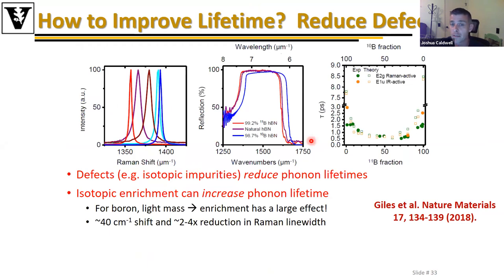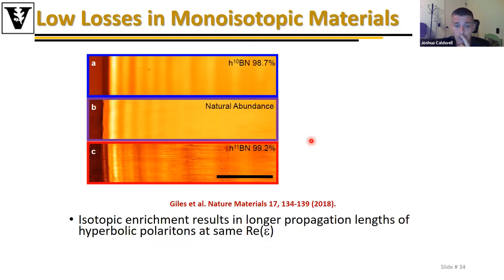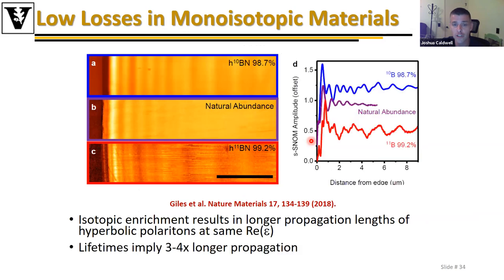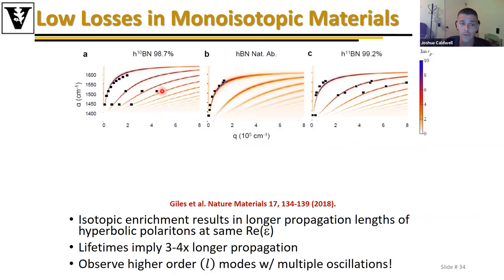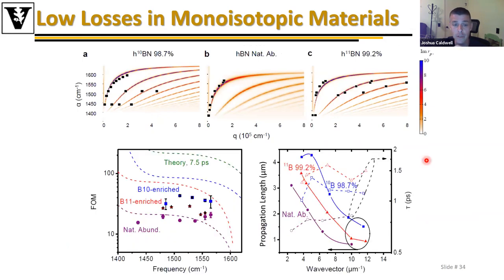And this also can provide significant improvements in lifetime. We've seen about a three to four fold improvement in the lifetime. More recent results have shown this to be even better, with the promise of getting up to about 14 fold. I'm not going to spend too much time on this, other than to show the line scans of these scanning near-field optical microscope maps of boron 10 enriched, boron 11 enriched, and naturally abundant. You can see these much longer propagating modes, which also support these higher order resonances present within these structures. For the first time, you could actually directly observe these.